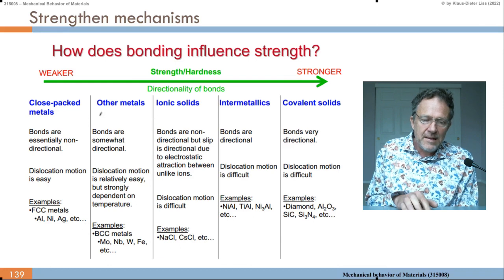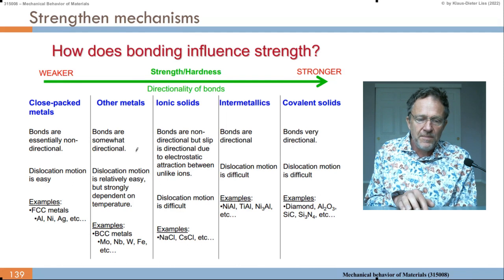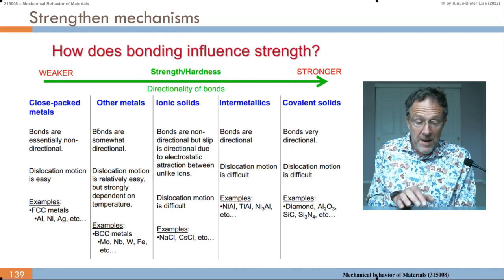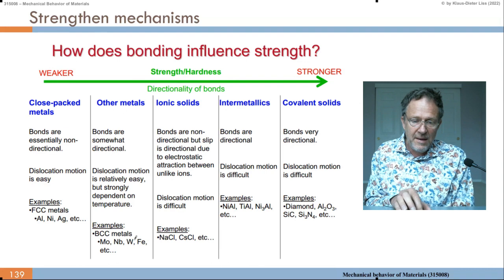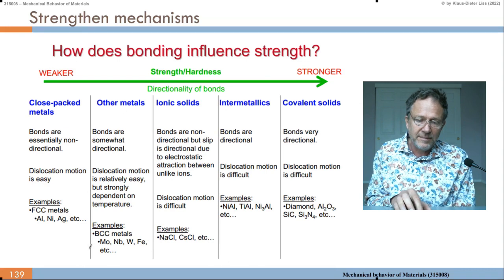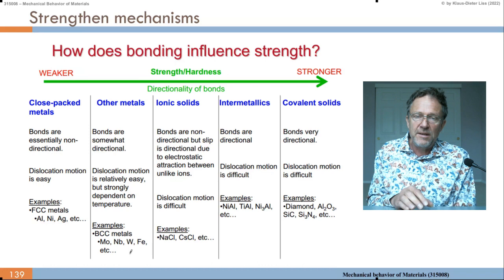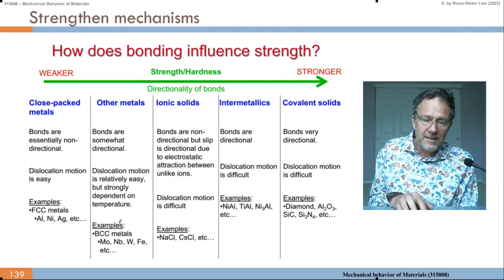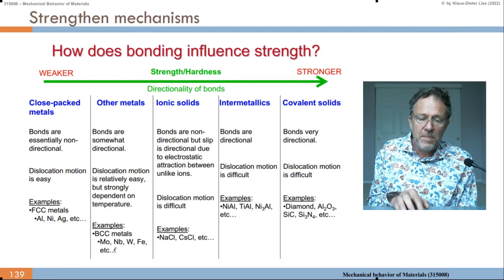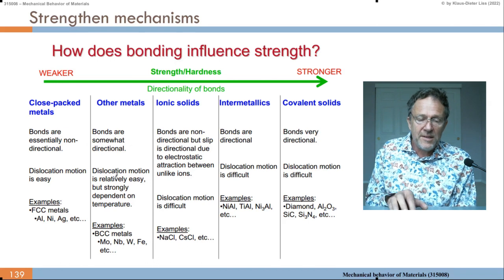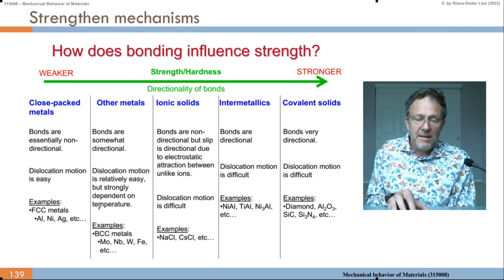The other metals, so we have somewhat directional bonds and interaction. That's why they're not close packed, like iron, the BCC iron, other BCC metals. So there's a reason why they are not close packed. If they would be spherical, then there would be an isotropic, there would be close packing. So they have some directional character or some nearest neighbor interaction. So then the dislocation movement is relatively easy, but strongly dependent on the temperature.